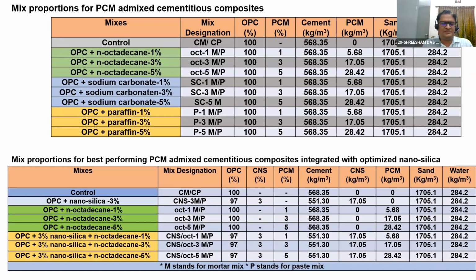What I've done, I will tell you. We have taken all these initial mixes, and from these we have chosen only the best performing mixes. First we checked that the phase change material doesn't hinder the hydration process too much. If it hinders too much, then it is not good for me. Out of these three, n-octadecane, sodium carbonate, and paraffin, we have realized only n-octadecane is performing the best. For my requirement, n-octadecane is the only one working with my material.